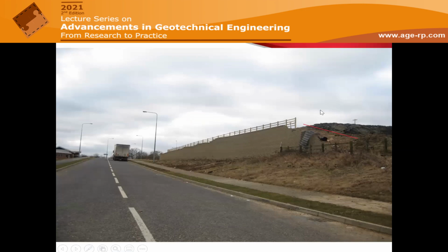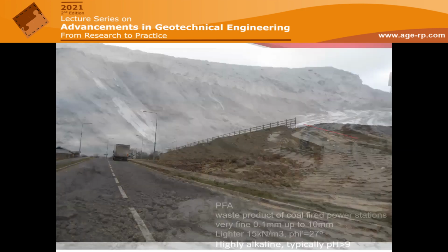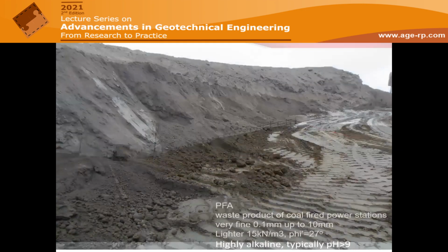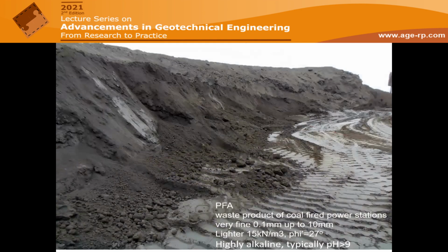And another material that is again a byproduct, a waste product you can say, of coal-fired power stations, is called PFA, or pulverized fuel ash. It's very fine, but it's granular, and in time it kind of cements. It's got an angle of friction typically around 27, and it's very alkaline. So if you're using polyester or steel strips, you have to be very, very careful and either factor it down a lot, or you can use high density polyethylene like we do, and it's absolutely no problem because they are inert to chemical attack.